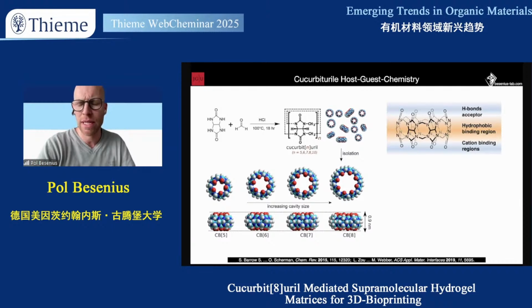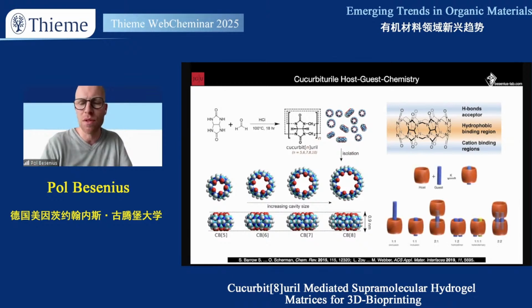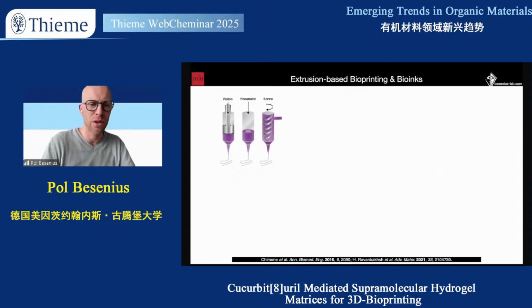So they're cyclic molecules. What makes them exciting and why we use them is because of the carbonyl, the basic carbonyl units at the periphery. They tend to bind cationic guests fairly strongly, and you then modulate the stability of those complexes by playing around with typical tools that the supramolecular chemist likes using, so hydrophilic-hydrophobic balance, as well as charge complementarity. What I will be focusing on is the cucurbituril CB8 unit, which has a fairly large cavity, so you can make homoternary and heteroternary complexes, in the sense that two guests fit into the same or different guests fit into the cavity of that unit.